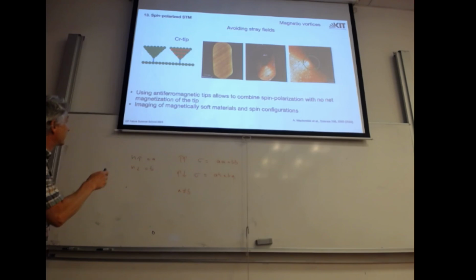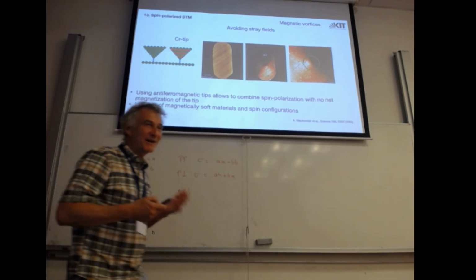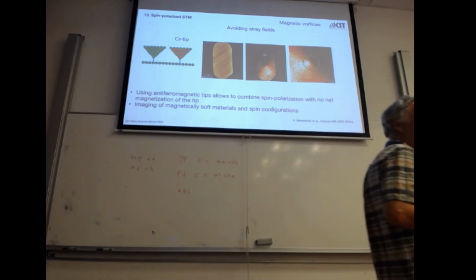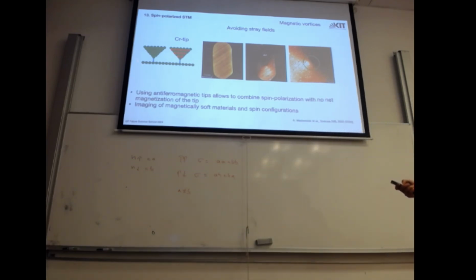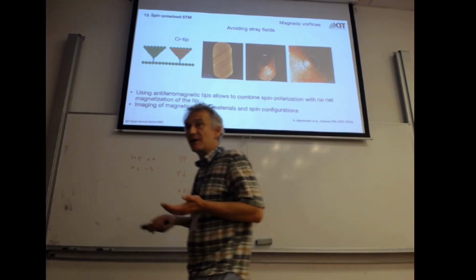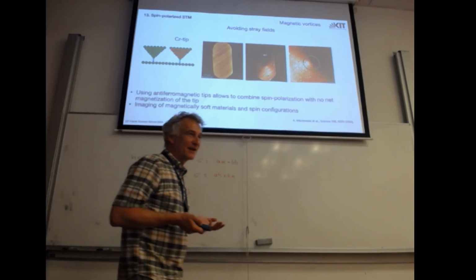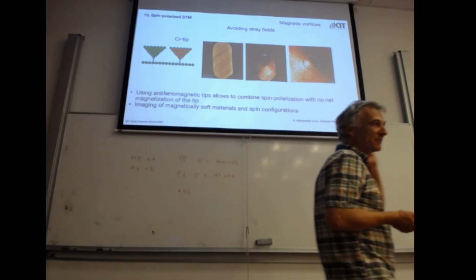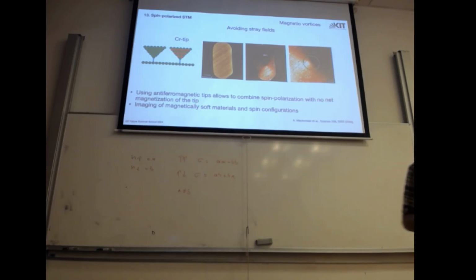So you have a magnetic tip here, and your surface, and the current is spin polarized. What you usually don't like is to use a bulk ferromagnet, because a ferromagnet has a magnetic stray field. This would act on the magnetization configuration of the sample. This stray field is about half of the saturation magnetization of the material. So iron will give you, roughly speaking, a Tesla of magnetic stray field. That's not really good, because maybe it moves the magnetic domains you want to image.